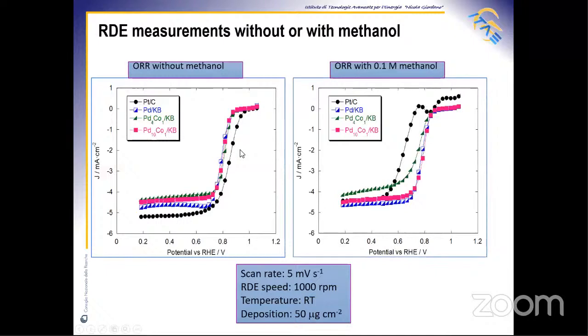These figures show the curves obtained in oxygen saturated perchloric acid without methanol and with 0.1 molar methanol solution. The methanol addition causes a shift of the ORR onset towards more negative potential values and a decrease of current. This is due to the mixed potential caused by the simultaneous oxygen reduction and methanol oxidation at the working electrode interface. This effect is more remarkable in the commercial 30% platinum on carbon, showing an evident methanol oxidation peak during the experiment.